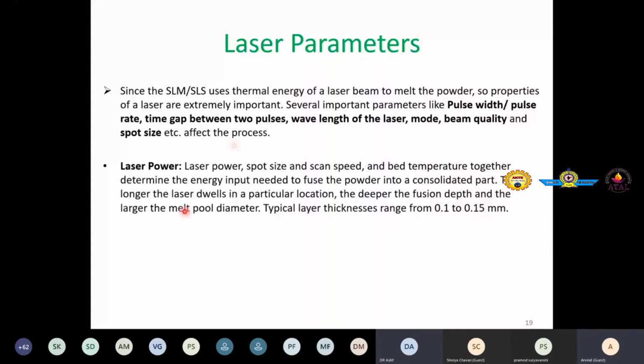Laser power, spot size, scan speed and powder bed temperature together determine the energy input needed to fuse the powder into a consolidated part. The longer the laser dwells in a particular location, the deeper the fusion depth and the larger the melt pool diameter. And in the SLM process, typical layer thickness ranges from 100 to 150 micron. In fact, this is large. There are processes where the layer thickness is about 20 to 30 micron. So you can imagine, if layer thickness is that small, your particle size should also match that layer thickness. It should be lower than the layer thickness. And when you can use finer particles and fine layer thickness, you can expect that the surface finish will eventually improve.